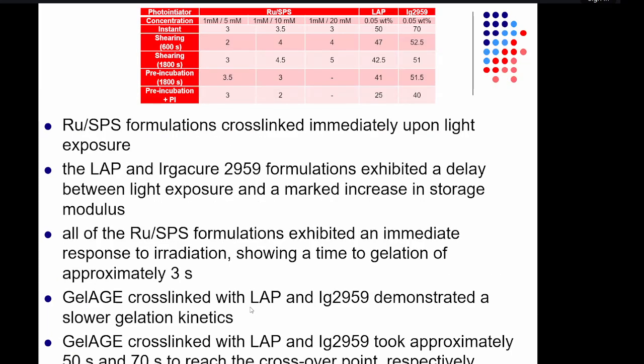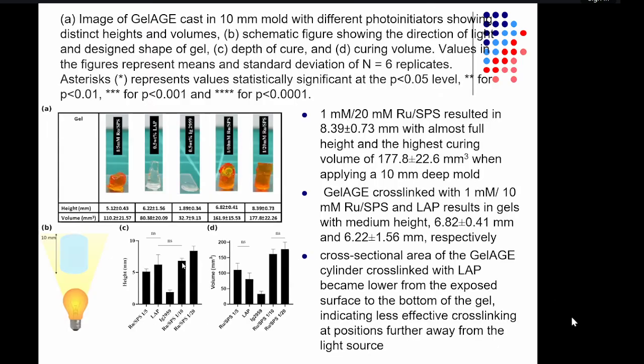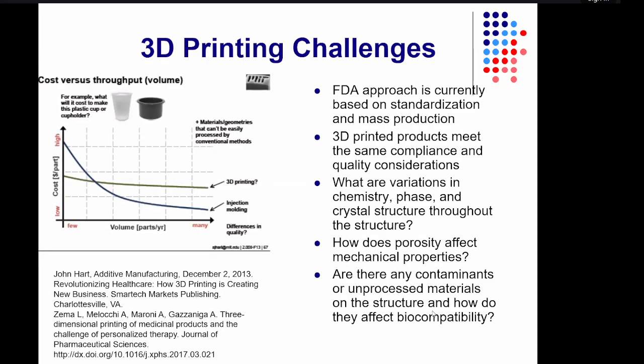So we have some recent study that we've published with University of Otago, showing that this material, ruthenium-based photoinitiator, has a very low time to gelation, as you can see here, as compared to the other materials. So much faster time to gelation, and it's a very good photoinitiator, as you can see here. You can get these large polymerized structures, and so this is one other class of materials we were looking at.